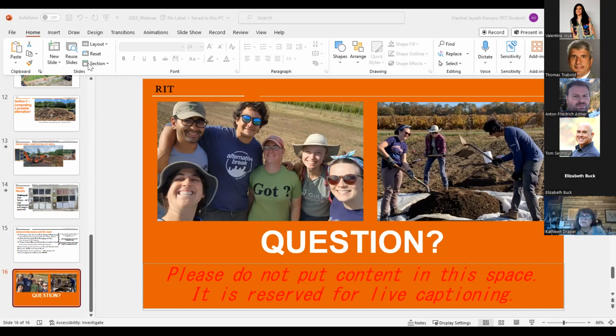Cool. Thank you. Then just one suggestion, possibly: if you are going to continue to test the degradation within a compost pile, it could be interesting, if there's bandwidth and funding, to have a compost pile that has 10 to 20% biochar, because it has been shown to heat it hotter. Agreed, it would be. Harshal has worked on that, actually. Excellent. Unfortunately it isn't part of this project, but it is absolutely something to keep in mind, where biochar does increase the biodegradation of the films.